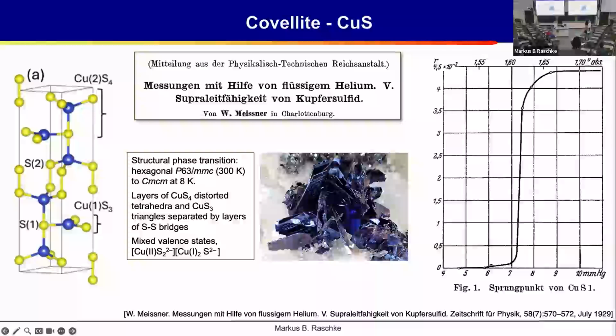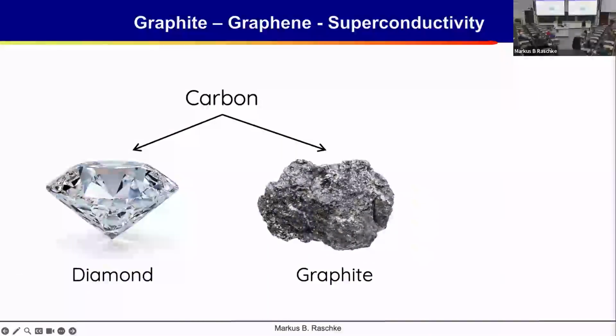also fairly low, but these are the original measurements from 1929, and these are heroic experiments at that time, with the limited technology available to actually make such measurements. And so here you see that sharp decrease, and there is a residual resistance. This is because of the lack of purity and the general difficulty of these measurements, but it indeed became superconducting, as described in this work in 1929.